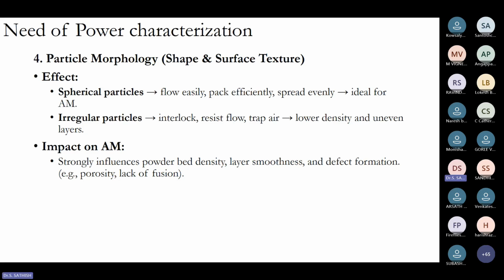Whereas if it has an irregular particle morphology, it will result in the formation of interlocks, or it will result in trapped porosities. So it will lead to variations in density at different places. This will result in additive components having defects, or the samples will not have a uniform surface roughness. And these are the things.